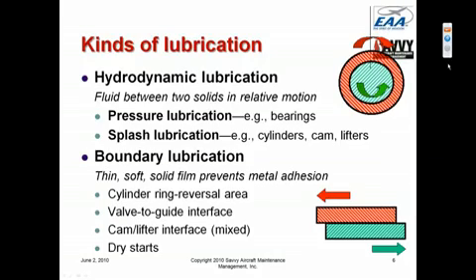And a good part of that oil mist winds up hitting the bottom of the piston, which accomplishes two things. One is it cools the piston, and the other is it goes through little holes in the piston to the oil control ring, which applies a coating of fresh oil to the cylinder walls every time the piston goes up and down. So that's how lubrication gets to the cylinder walls. It doesn't get there under pressure. It gets there by splash. And once again, the same thing is true of one of the other real critical interfaces in the engine, the cam and lifter interface, which again has no pressure lubrication. It's lubricated by splash oil.